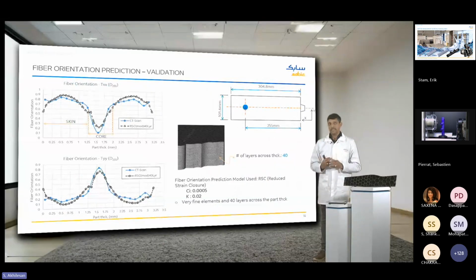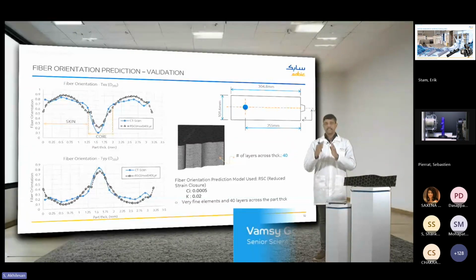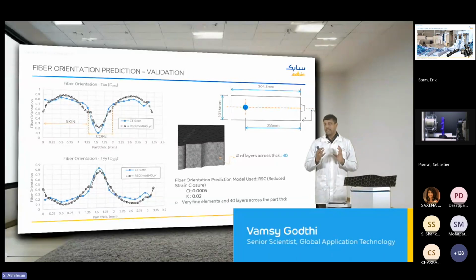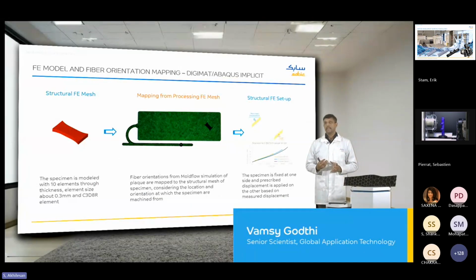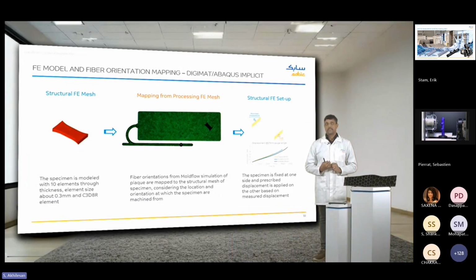Apart from this, we also look at sensitivities that come from the meshing itself. What we have observed is you need to have a sufficiently fine mesh in order to capture the skin core effect, and also a sufficient number of layers through the thickness to accurately predict the randomness that comes in the core part, in the center part. And once we have done this, we go to the next step, which is the structural validation.